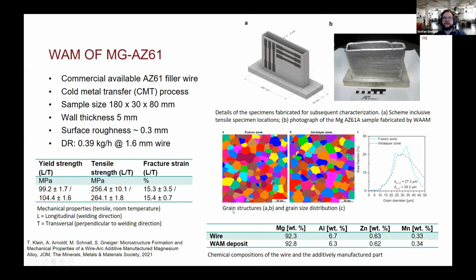Also, the grain structures are very comparable, in the fusion zone and also in the intralayer zone. The fusion zone is the zone exactly between two single layers, and the intralayer zone is in the middle of one layer. In both cases, they are quite comparable, and we have an average grain diameter of about 27 to 30 microns.